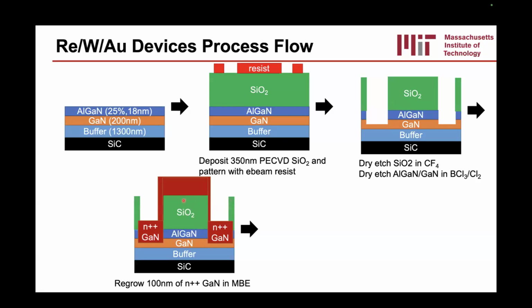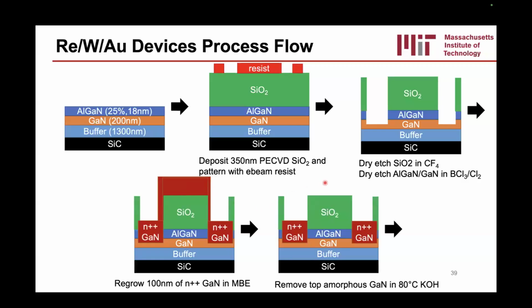It ends up getting all over the place here, but if we do a little bit of hot KOH, the GaN on top here is amorphous, and we can remove it very nicely.